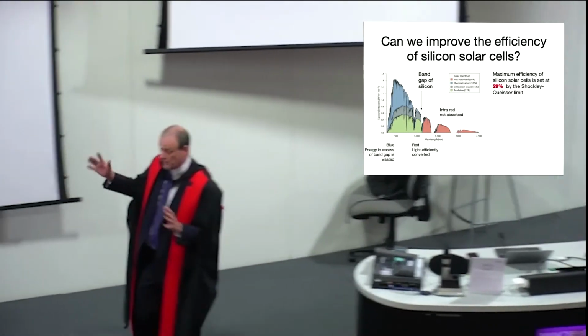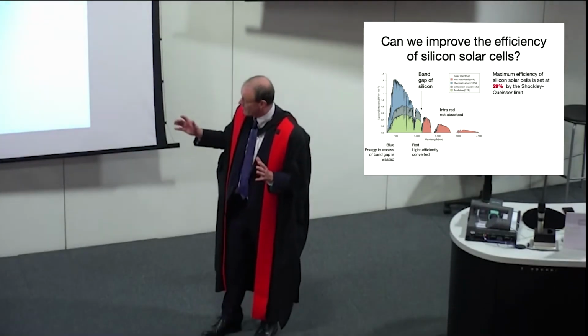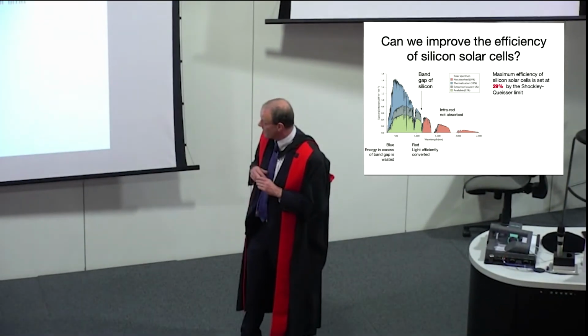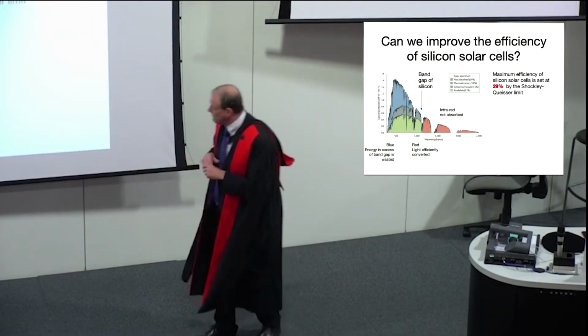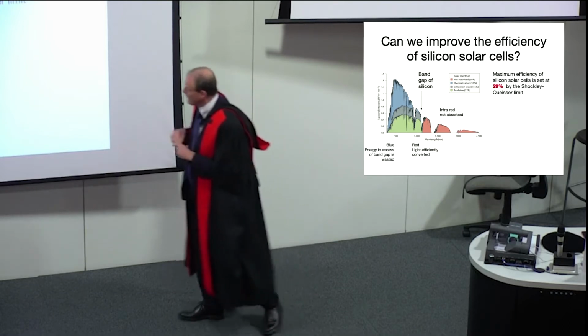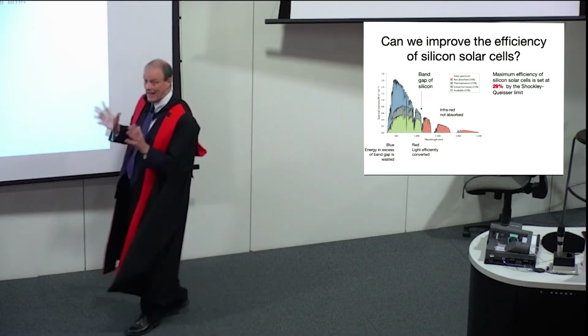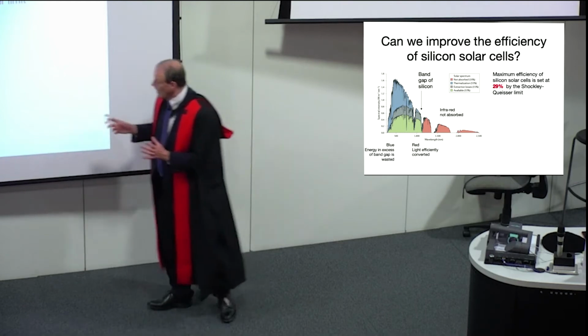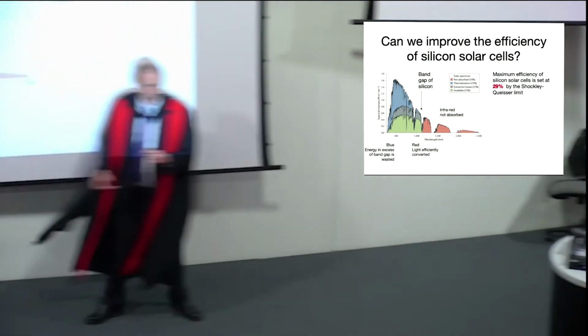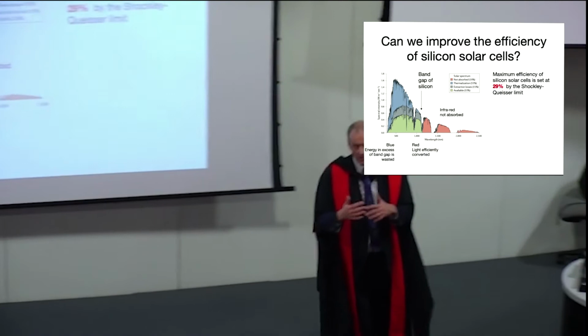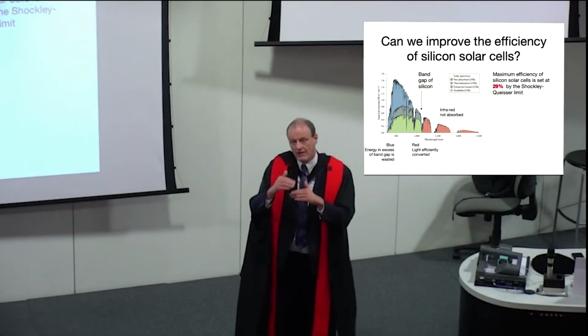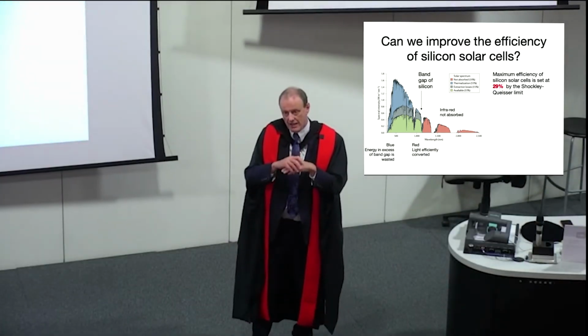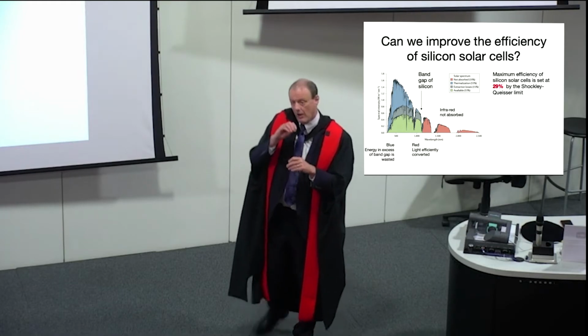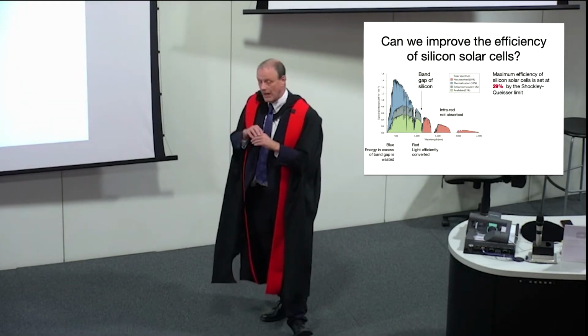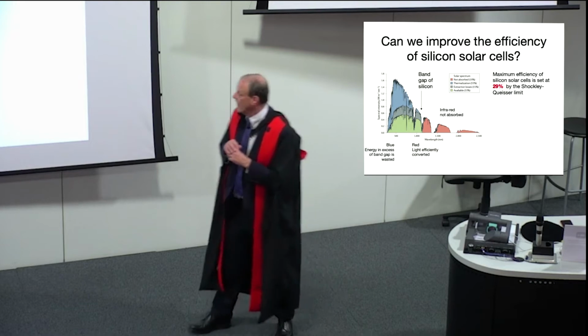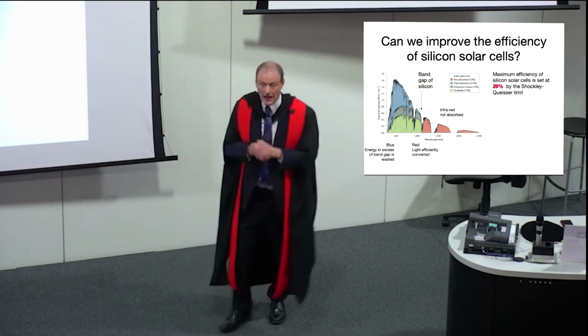Sunlight has a spectrum of colours that come out of the sun, which is expressed here. And it turns out for a silicon solar cell, or indeed any semiconductor solar cell, the long wavelength stuff is not absorbed. So the semiconductor has a band gap. That's the minimum energy that's needed to promote an electron from the valence band to the conduction band. So if the photon energy is less than the band gap, nothing happens.